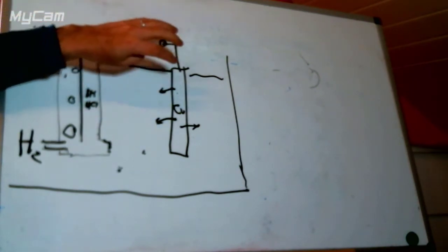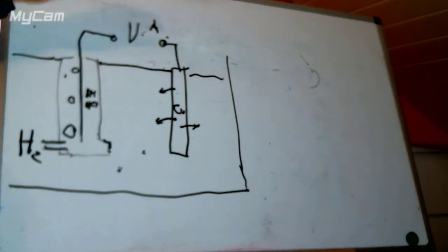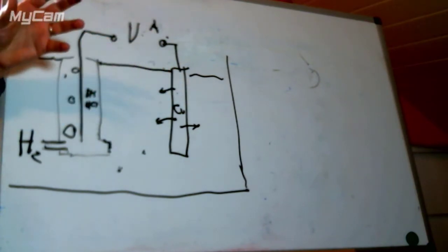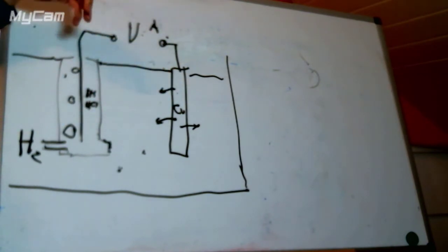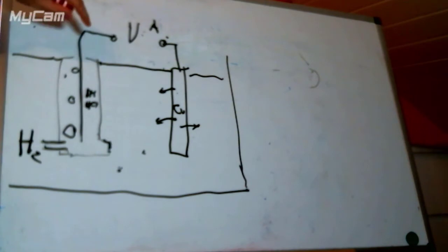and so we can think of the current as telling us something about the kinetics. Depending on what we do with our geometry, it might tell us different things about the kinetics, but the current is telling us about the kinetics, how fast does the copper dissolve, and the voltage is telling us something about the thermodynamics, how strongly does the copper want to dissolve, giving it a personality which we shouldn't do. Just reminding you that that's a bad thing to do, but I do it anyway. I'm sorry about that. So we've got copper dissolving in this particular case, and we can see two extremes.